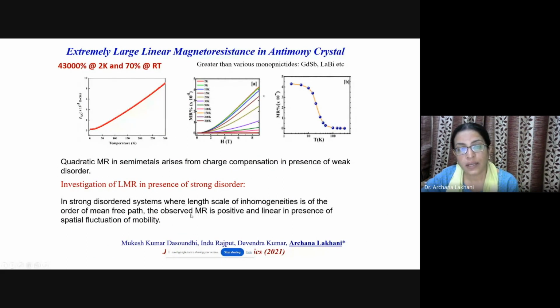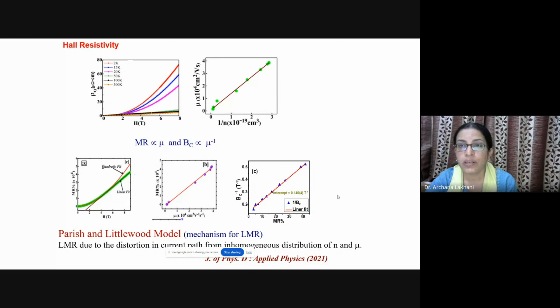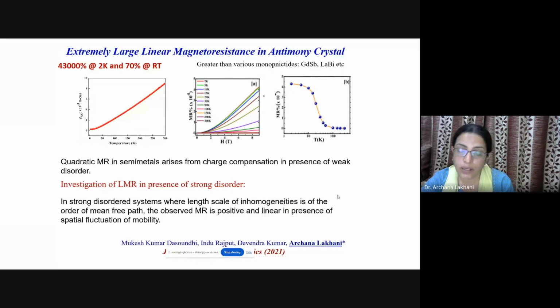We analyzed this. It had a classical origin, which was explained by the Parish and Littlewood model. It says that in strongly disordered systems, where the length scales of the inhomogeneities or disorder present in the system are of the order of the mean free path, the observed MR is positive and linear, in the form of spatial fluctuations in the mobilities. This was the case in this antimony crystal, and it had 43,000 percent magnetoresistance at 2 Kelvin and 9 Tesla, which is even larger than some of the known rare earth monopnictides like GdSb and LaBi also.